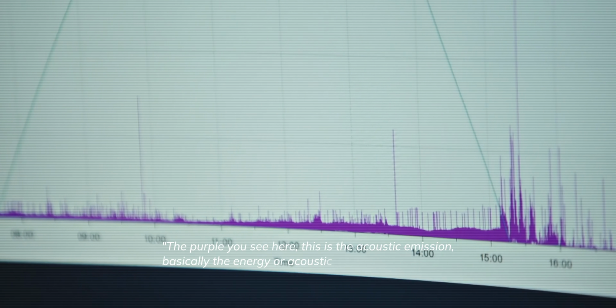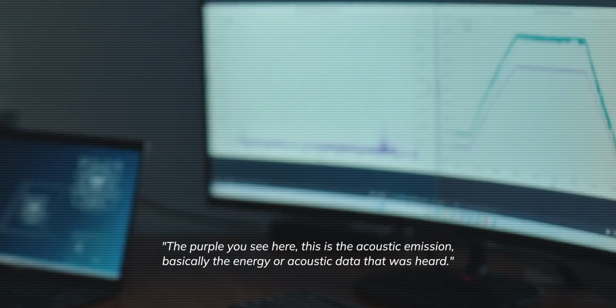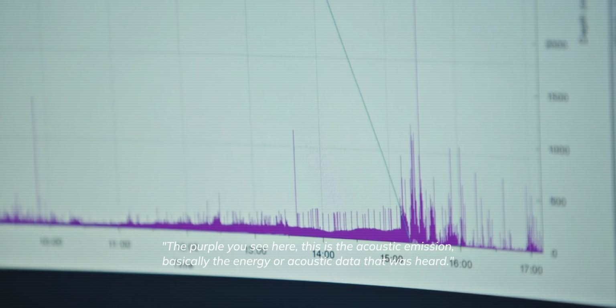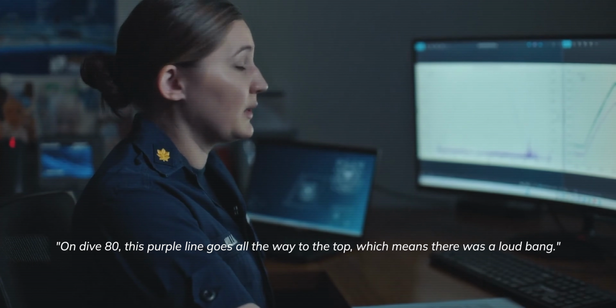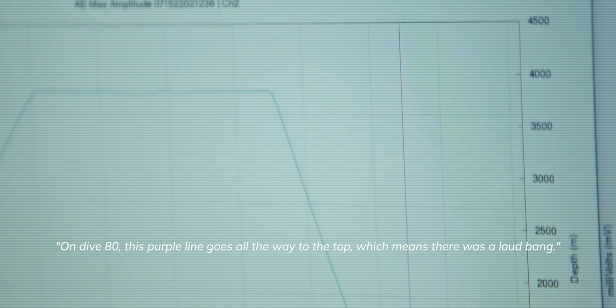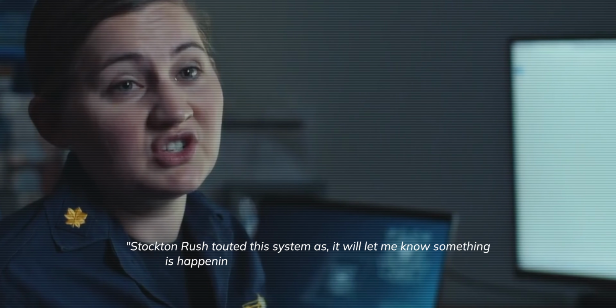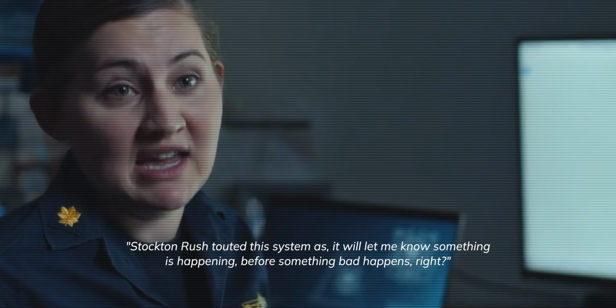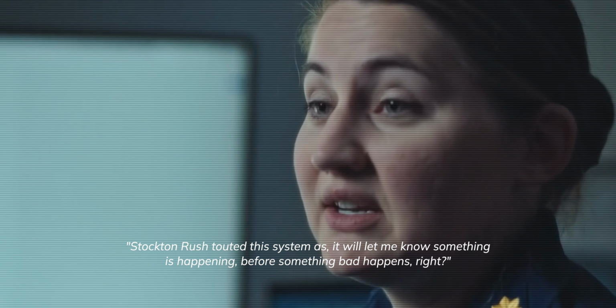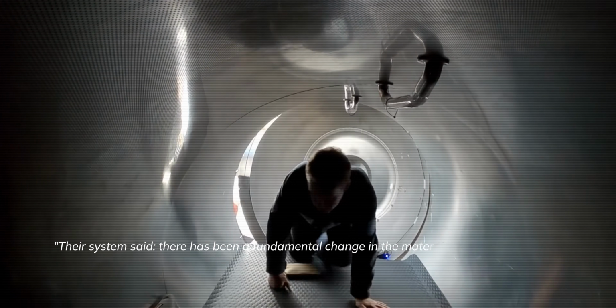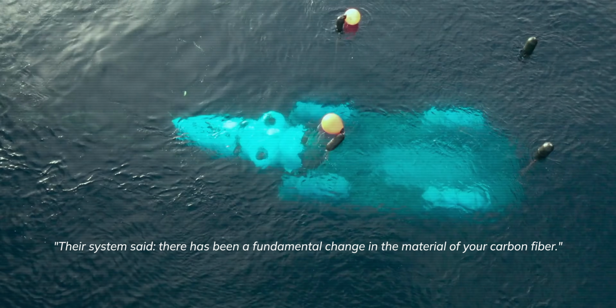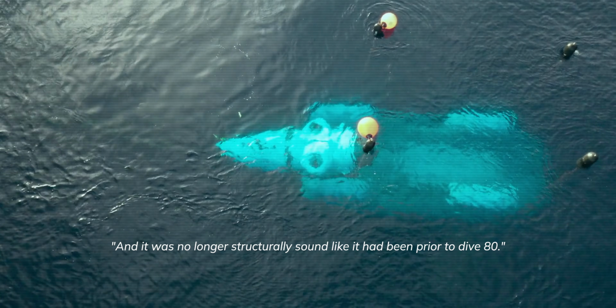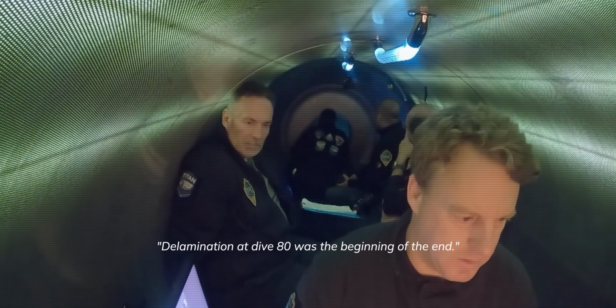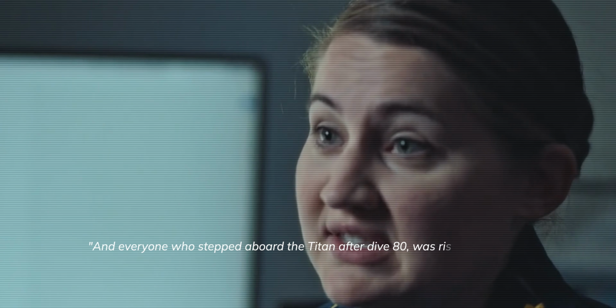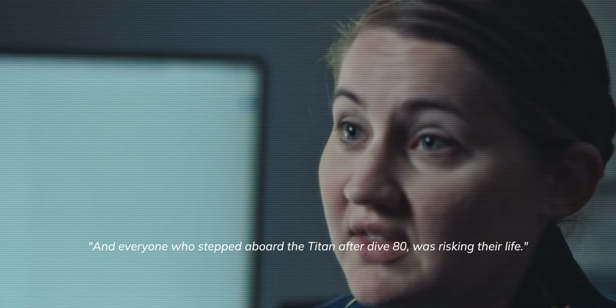The purple you see here, this is the acoustic emissions, basically the energy or acoustic data that was heard on Dive 80. This purple line goes all the way to the top, which means it was a loud bang. There is this huge amplitude. Stockton Rush touted this system as it will let me know something is happening before something bad happens, right? Their system did that. Their system said there has been a fundamental change in the material of your carbon fiber, and it was no longer structurally sound like it had been prior to Dive 80. Delamination at Dive 80 was the beginning of the end. And everyone that stepped on board the Titan after Dive 80 was risking their life.